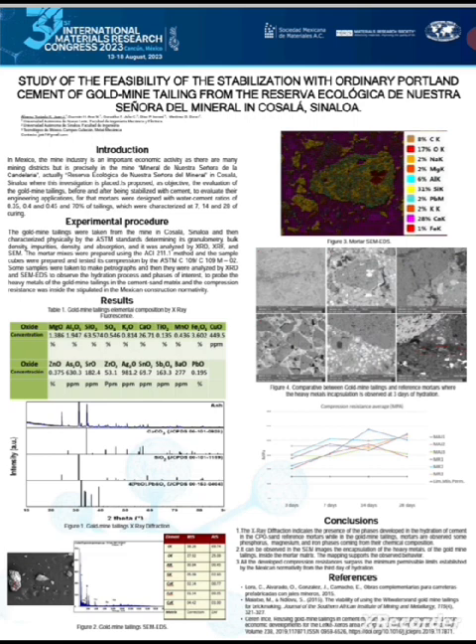And the X-ray diffraction demonstrated the presence of the phases of lead, silicon oxide, and calcium carbonate, being these last two of good behavior with cement. In addition to what was known by XRF and XRD, the SEM EDS showed the same chemistry, but the relevance of the SEM was the mapping of the mortar of cement sand gold mine tailings at 70% of the fine aggregate weight that showed that the heavy metals were in fact trapped in the mortar matrix, so the mix was fulfilling its objective of trapping the toxins in there.